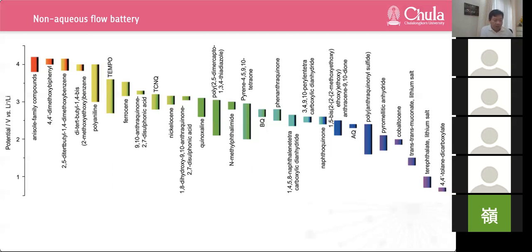The organic and organometallic compounds have a wide potential window in the range of 0.7 volt to more than 4 volt. And the redox potential of promising candidates used as anode and cathode material should be lower than 2 volt and close to or higher than 4 volt to achieve high cell voltage, which is greater than 2 volt. Some of the organic material with proper modification to tailor redox potential, solubility and electrochemical activity have potential for non-aqueous